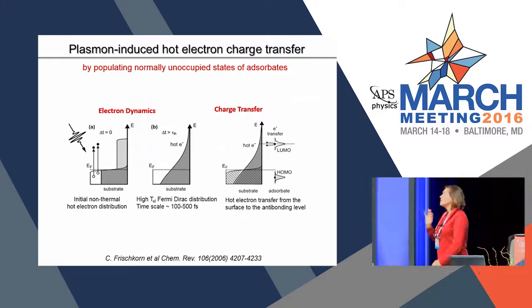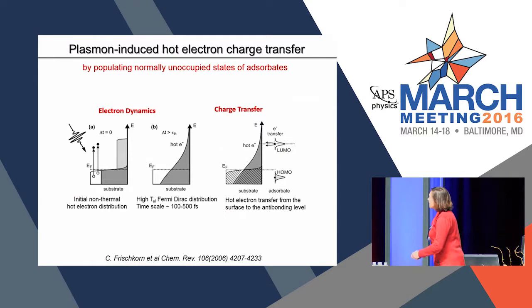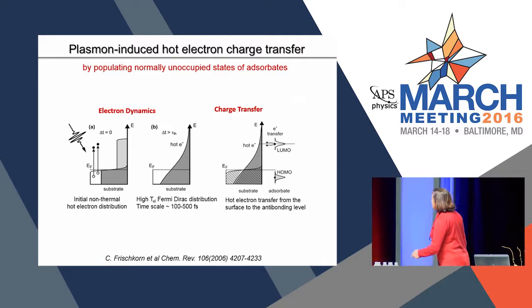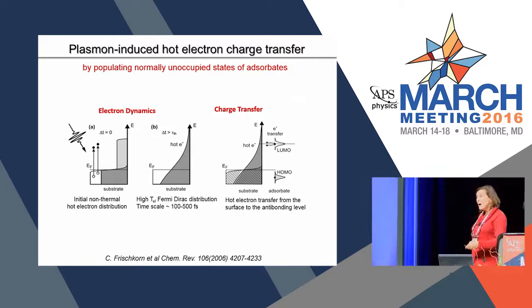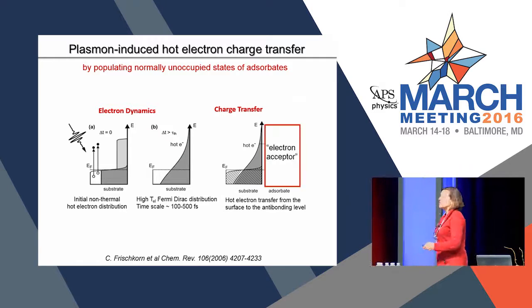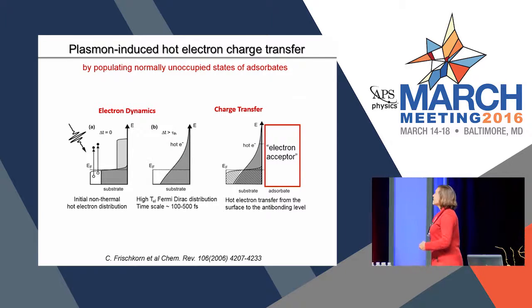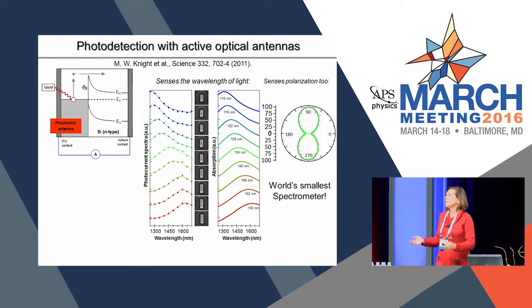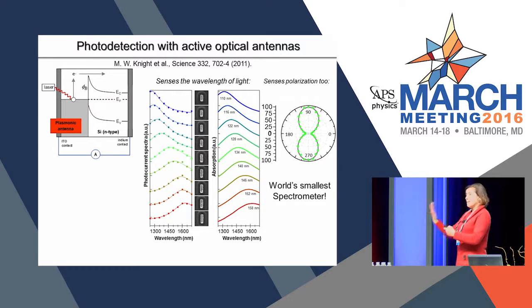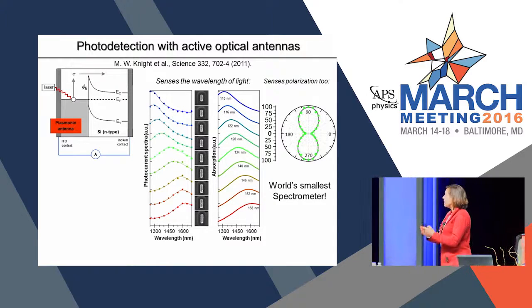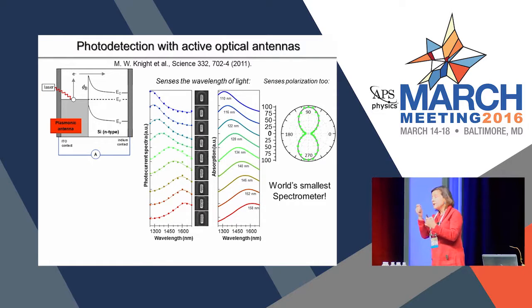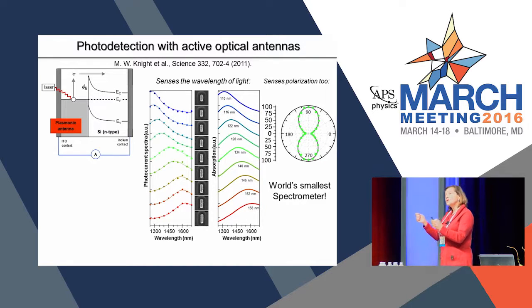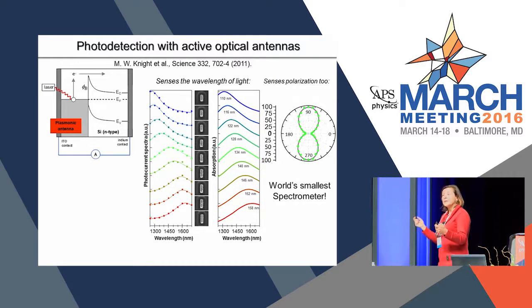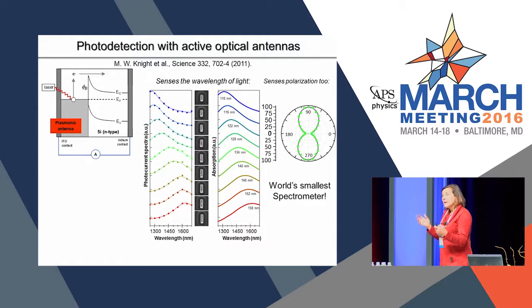So this is something that the chemists knew quite some time ago, and looked at how one can basically excite the electron fluid, and then for hot electrons, how hot electrons could transfer into the unoccupied state of a molecule and do chemistry. But we don't have to do this with molecules. We can do this with any kind of electron acceptor, so we can do this with a very simple solid. So let's look at an experiment that we can all understand very easily. We can make a Schottky barrier where the metal of the Schottky barrier is a little nanorod. And so this is the nanorods here in the center. If we optically excite the nanorod, we excite a hot electron. If the hot electron has enough energy to make it over the Schottky barrier, it will transfer into the semiconductor, and we can then collect this as photocurrent. So I'm no longer limited for generating photocurrent by the band gap of the semiconductor.